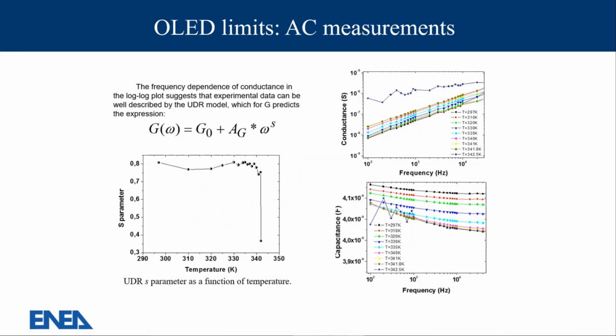We can model this. If we remove the series resistance, the conductance will be almost parallel, and we can model it. If we model our device with the universal dielectric response, we have the possibility to monitor the S parameter, which is the exponent of the pulse that we apply to our device, and it is possible to see another time that this exponent will change drastically approaching the glass transition, then it will change definitively at the end.